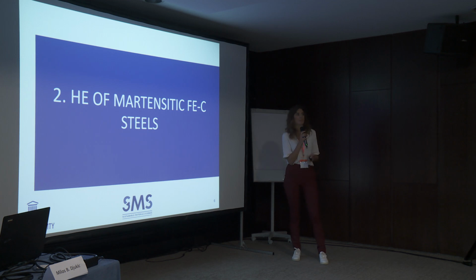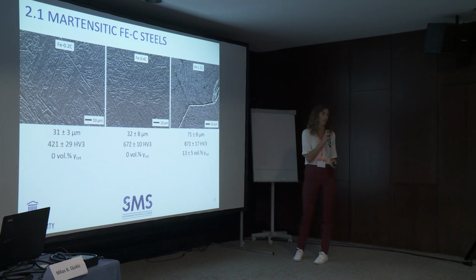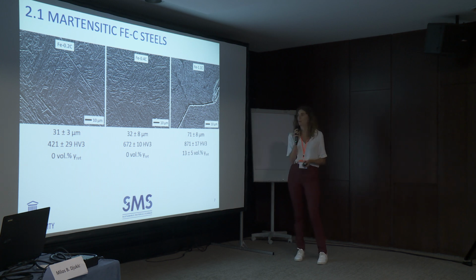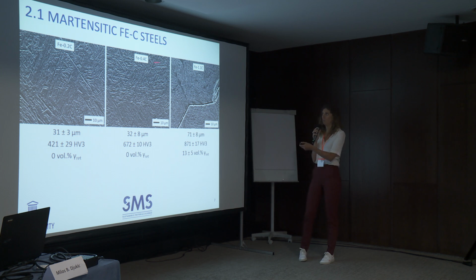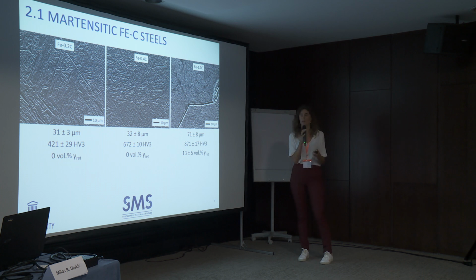So how does the hydrogen embrittlement of martensitic iron carbon steels look like? Well, I worked with 3 alloys. So these are simplified iron carbon martensitic steels with 0.2, 0.4, and 1.1 weight percentage of carbon. The generic properties are also given in this presentation. So the 0.2 and 0.4 carbon steel have a very similar parent austenite grain size of about 30 micrometers. And the 1.1 has a much higher parent austenite grain size.